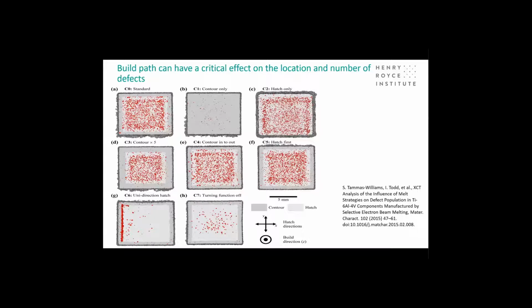And we'll see later in this talk that defects that are positioned near the surface often are more likely to be critical defects. And so if you can identify build patterns that reduce the likelihood of large defects occurring near the surface, that can be an important way of increasing the lifetime of your components.